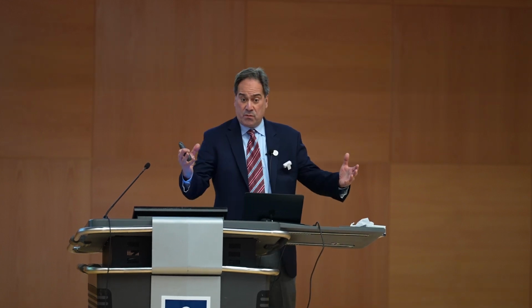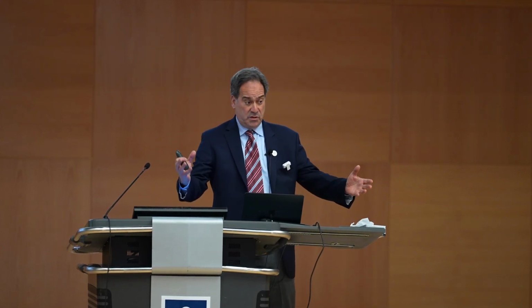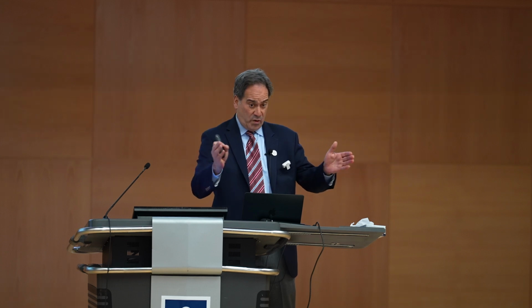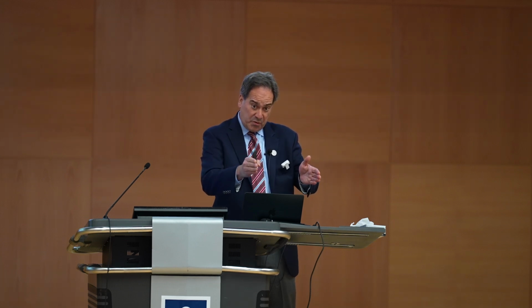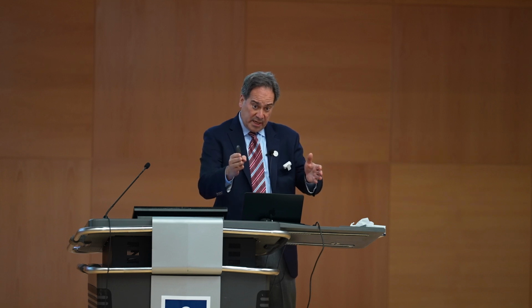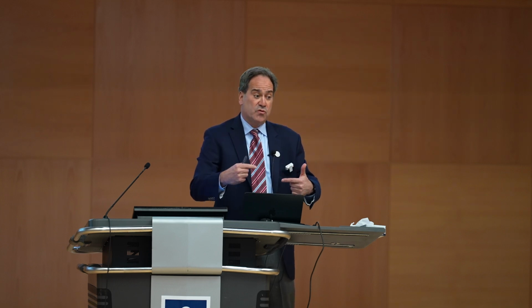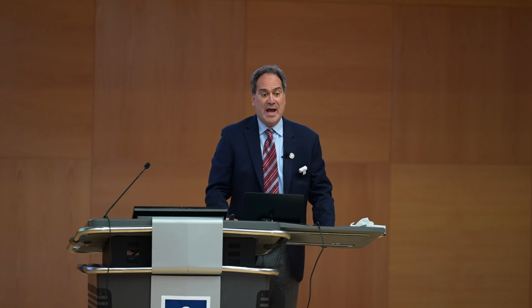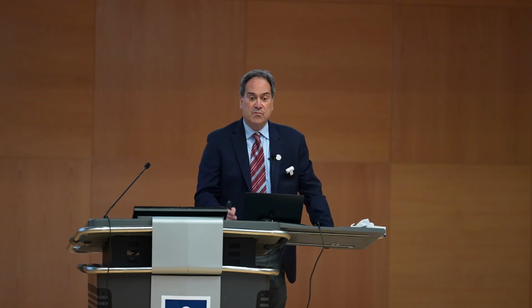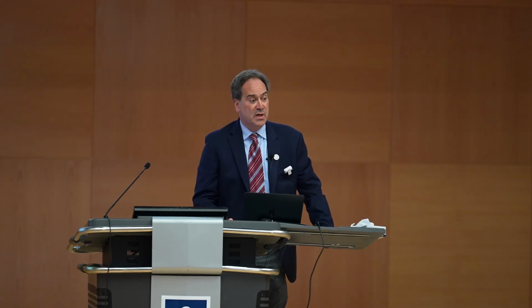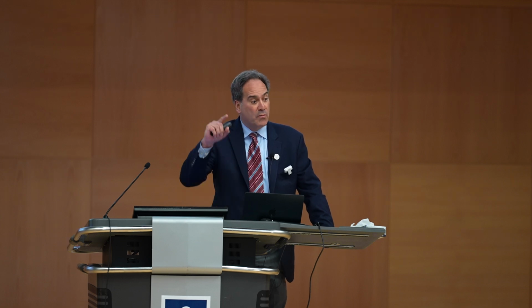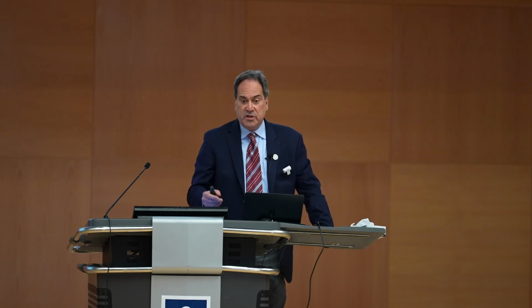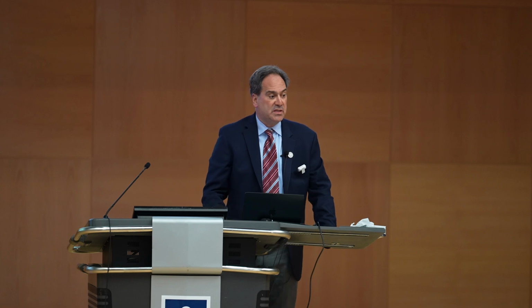So now with dip pen, what you would do is you would take molecules, coat them on AFM tips, run an AFM experiment, establish a point of contact, let water collect, and then use the chemical driving force of molecules reacting with an underlying substrate to drive the movement of those molecules to the surface, and you could create add layers that were one molecule high. Pretty interesting concept. Published it in Science magazine.